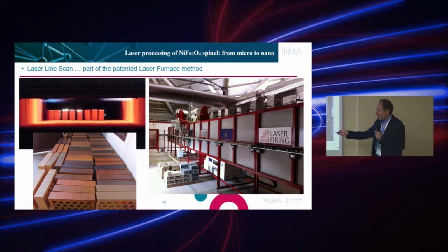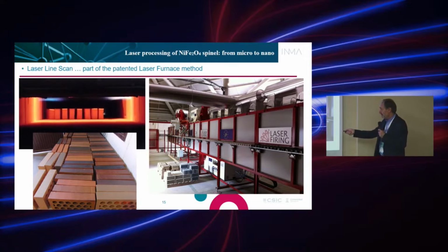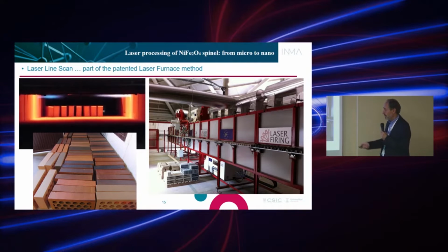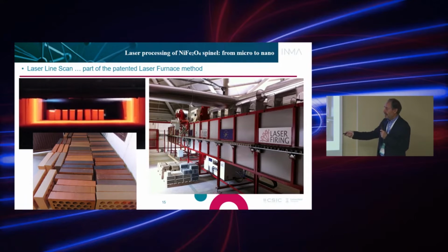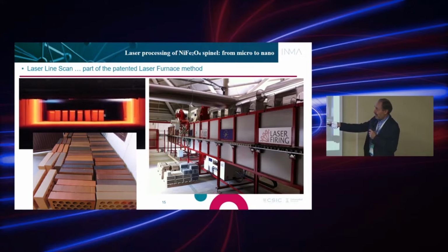And you see here, working in large scale. This is a 15-meter long furnace in a project we did. And this is the resultant products. In this case is brick. And you can see you can get very different surface finishes, even with the same clay. So that depends on the emission conditions and on other parameters like the traverse rate of the materials going through the furnace. Even when they are misaligned, they come out uniform, and this line is very well aligned